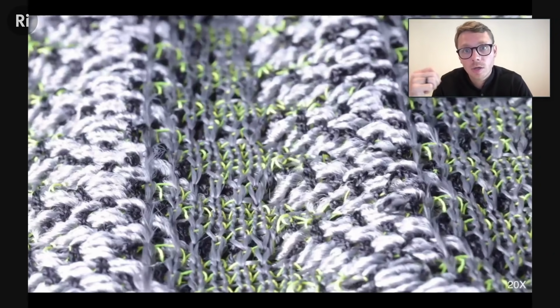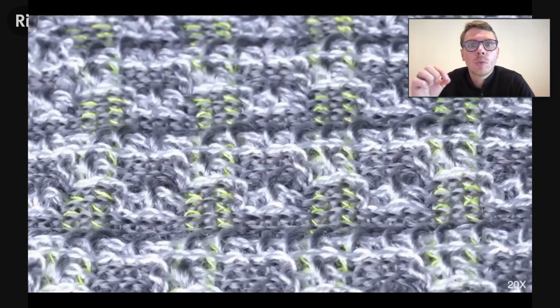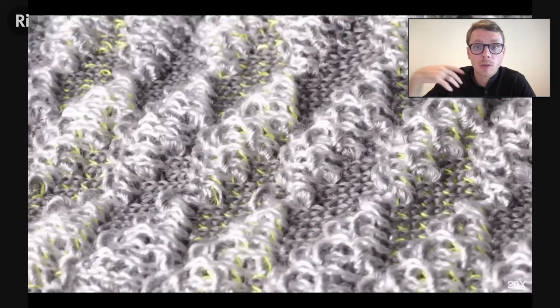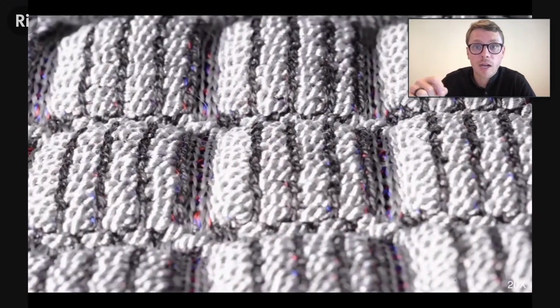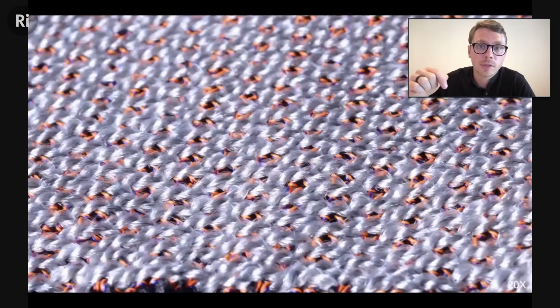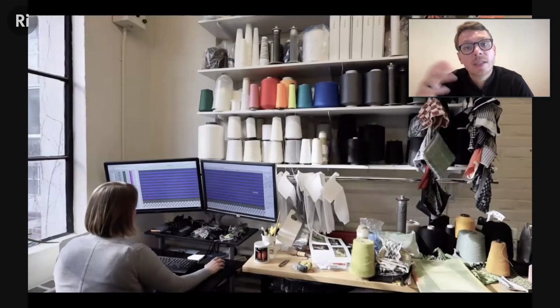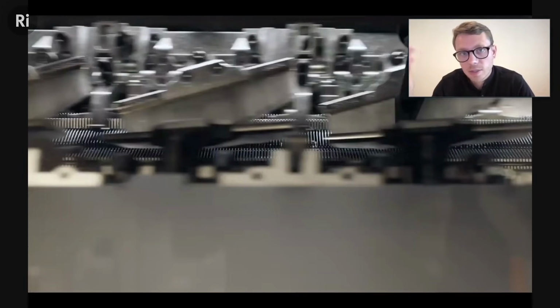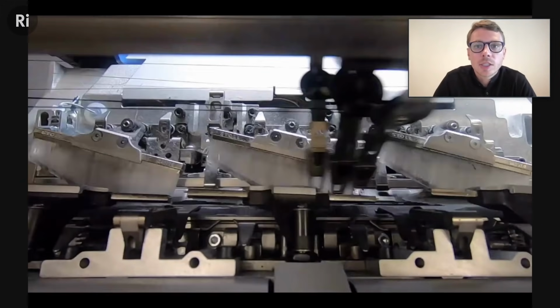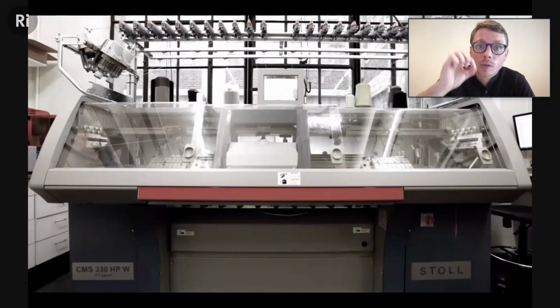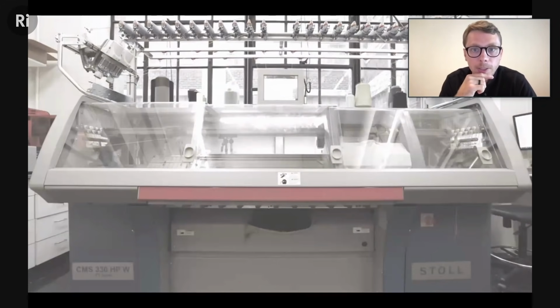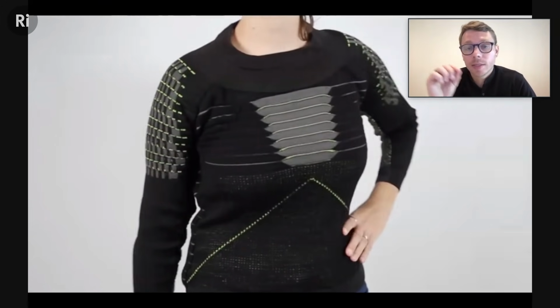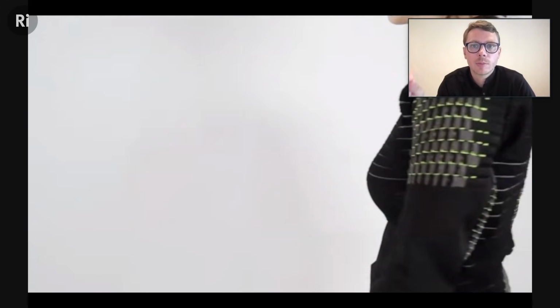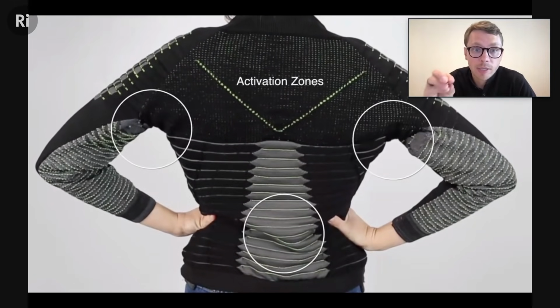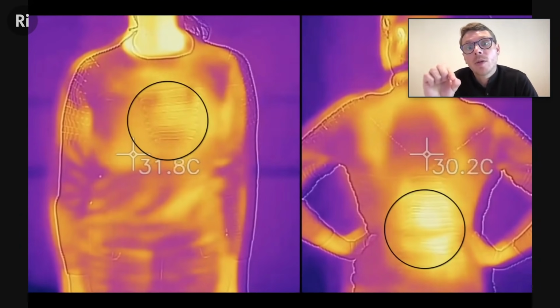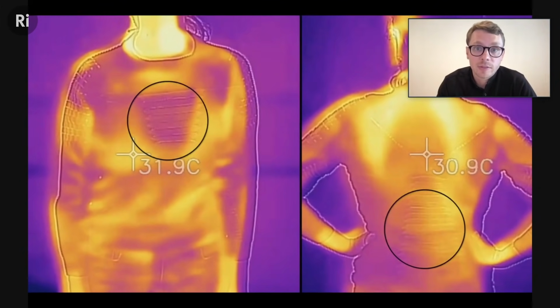The fiber is then twisted into yarns and then we CNC knit. So we can actually change pixel by pixel in a three-dimensional structure the material and the fiber and the color, every single pixel, much like 3D printing, but with knitting. And this is how you get Nike's Flyknits or Adidas knits or any of the knitting technologies, through this industrial knitting machine where you can change the fiber pixel by pixel, basically stitch by stitch. And so we do that in the same way, just like the 4D printing, we change the material properties. We have our own fiber that has specific material properties, and then we design the knit structure in order to have different behaviors.